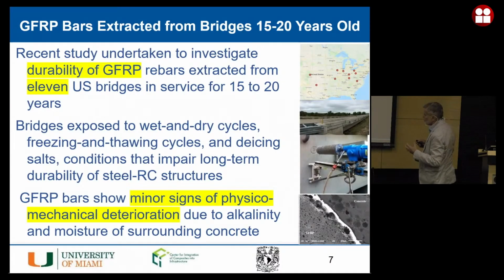So one of the issues that came to the table in the 90s, before many of you went to school, right? Maybe you were in primary school or even in kindergarten, there was the question of durability of the glass as a fiber, because glass is not really performing well in an alkali environment, like concrete typically has a pH of 12 and above, right? So the issue of durability was brought up and discussed many, many times, but we have finally demonstrated, not only with accelerated tests in the laboratory, but also in the field, that this durability is there. And the primary reason not only is because the quality of the fibers has improved, we now use ECR glass, but also because of the protection that the resin affords, okay?